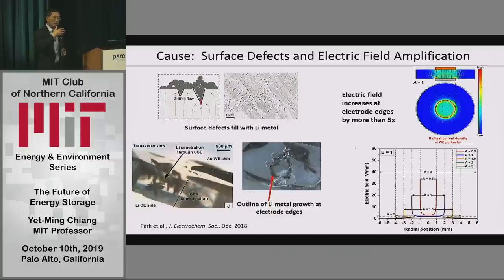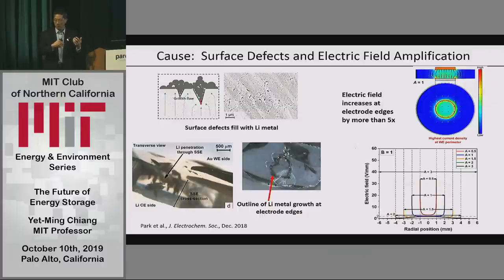When you consider what has to happen as you deposit this metal, there has to be a volume expansion to accommodate the metal. And so that metal can either open the crack and allow the dendrite to go forward, or it has to be extruded or forced out the back side of the crack. So in this picture up top here, the metal will deposit where that red arrow is. And either it has enough time and low enough, let's call it viscosity, so that it can flow out, or it's going to open the crack.